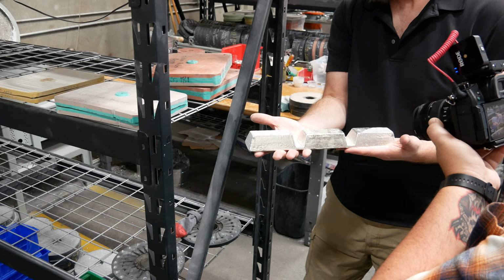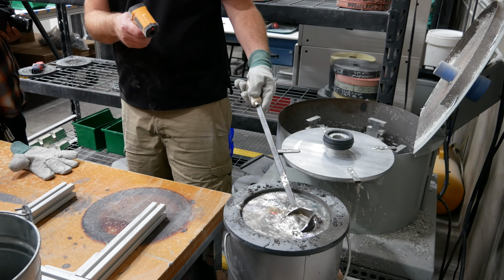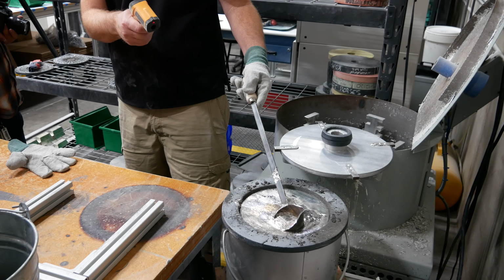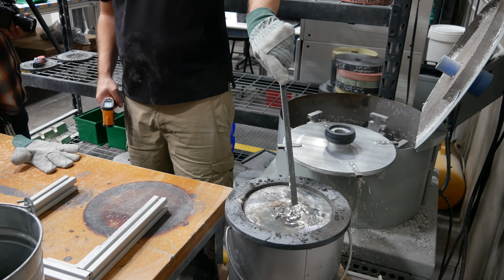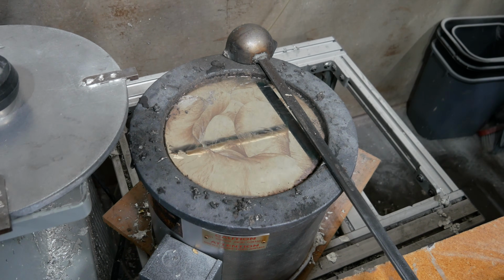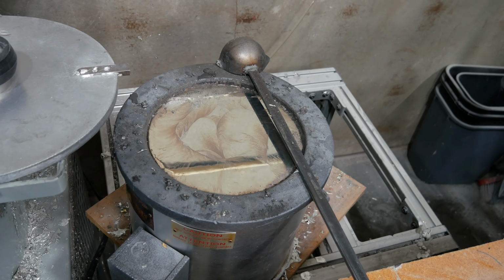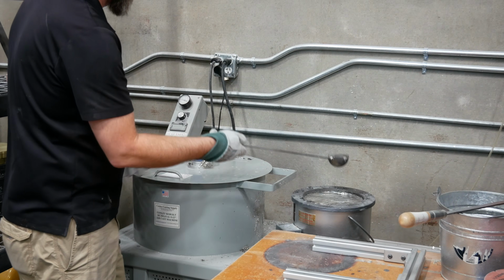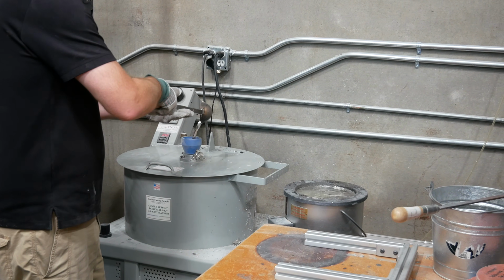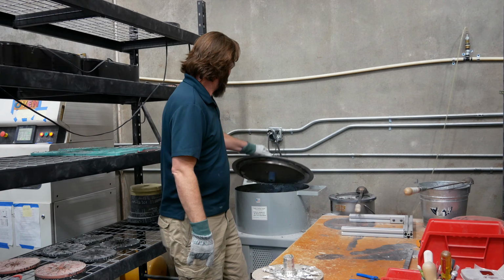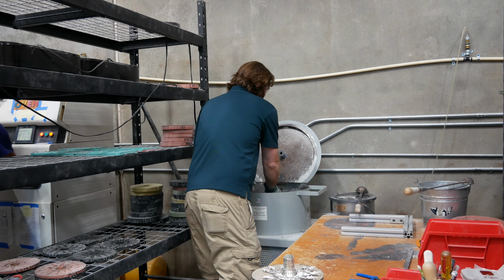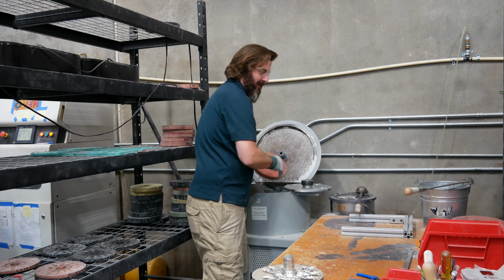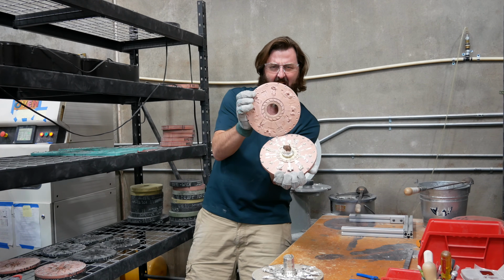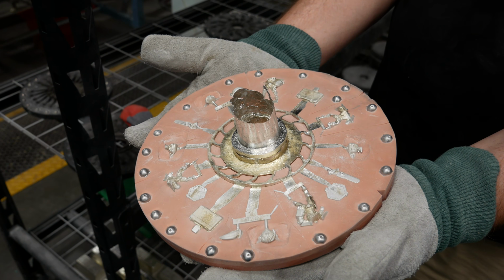Next up, metal. Blocks of pewter are melted down and cast into miniatures. This liquid metal is somewhere around 500 degrees Fahrenheit. The alloy in there is about 95% tin, with the remainder composed mostly of antimony and copper. A ladle of liquid is poured into the spinning mold. Centripetal force fills the cavities. The molten metal cools into a solid, and you've got yourself some nice pewter miniatures.